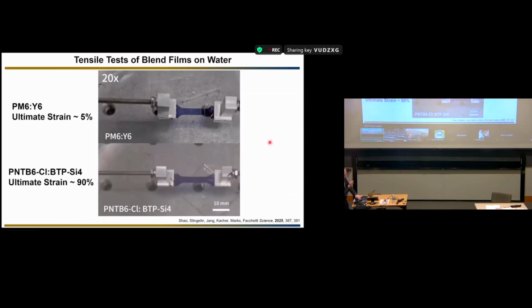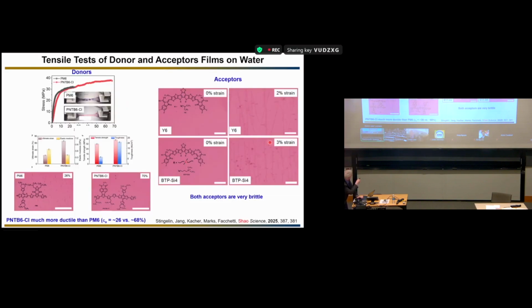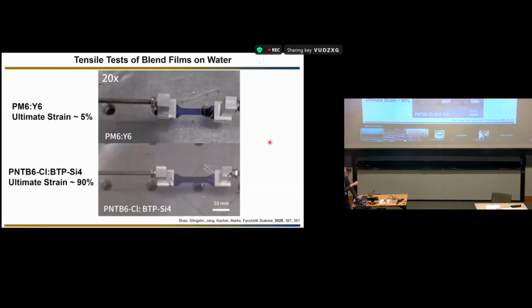In this video, I don't know if it's going to work. This is the control device. This cracks on the order of 5%. The pure PM6 cracks at about 26%, but when you throw in this acceptor, the blend becomes more brittle. This is expected. If you look at this video, we start stretching, and it cracks right away, at about 5%. This is the new blend, using the new donor and the new acceptor. We start stretching, you keep stretching, and you go to about 90%.